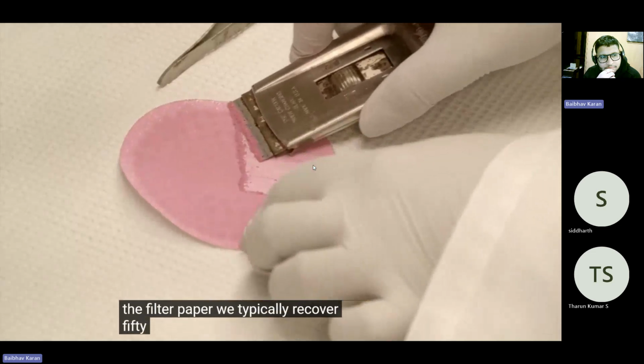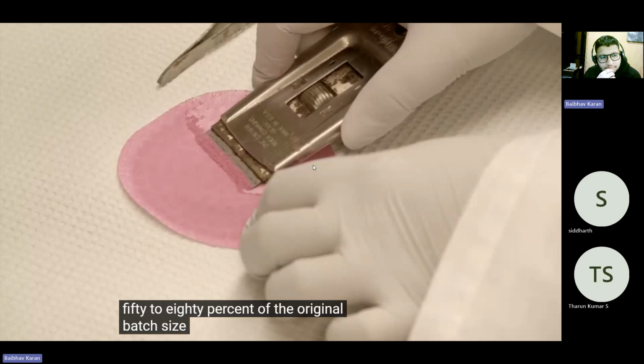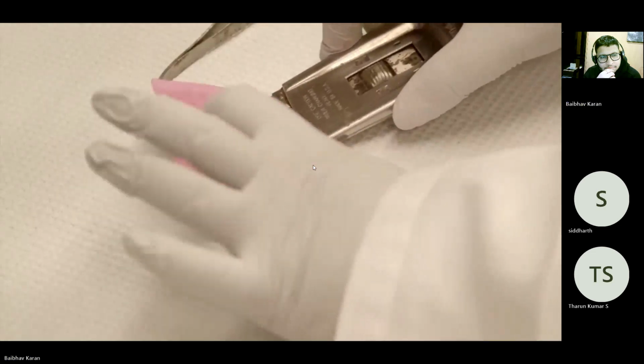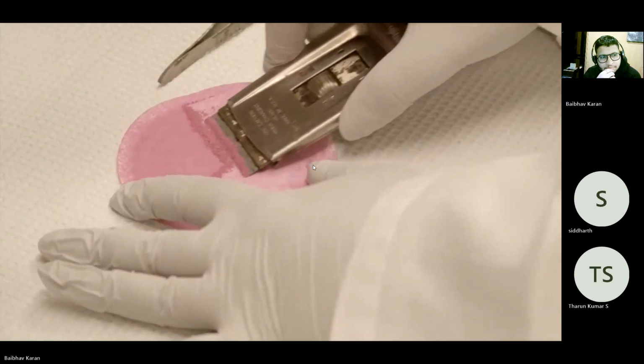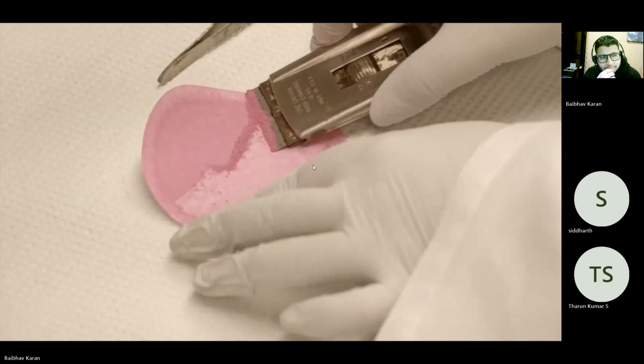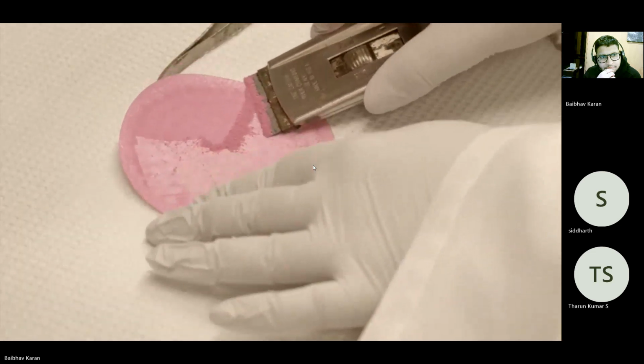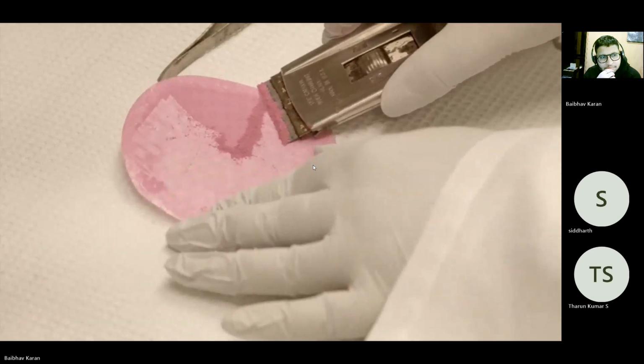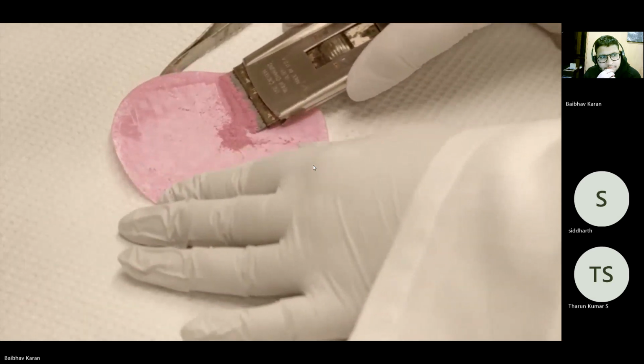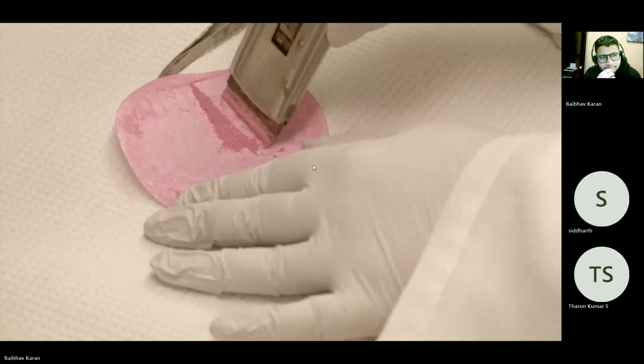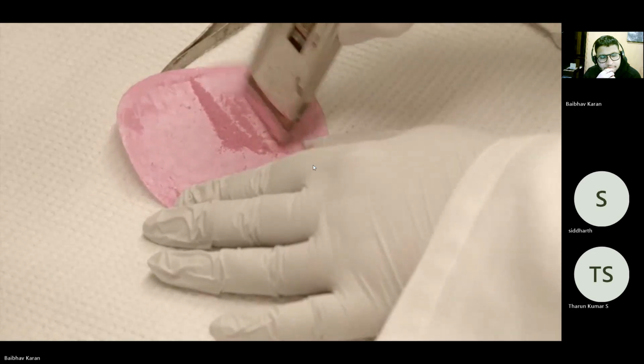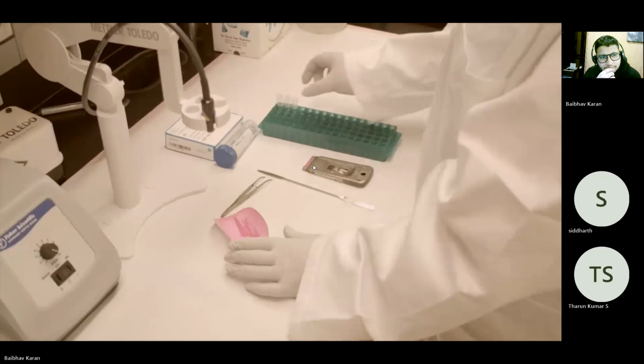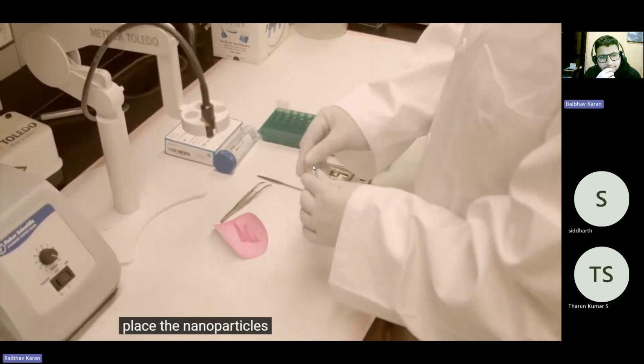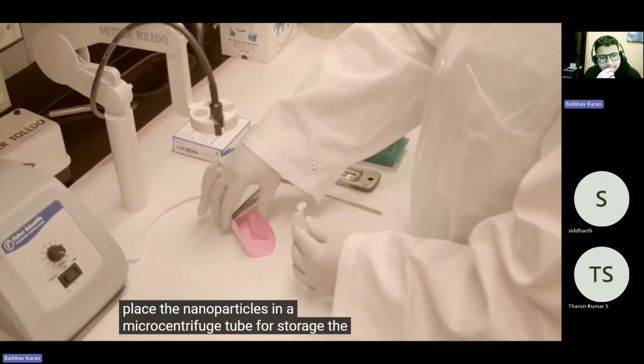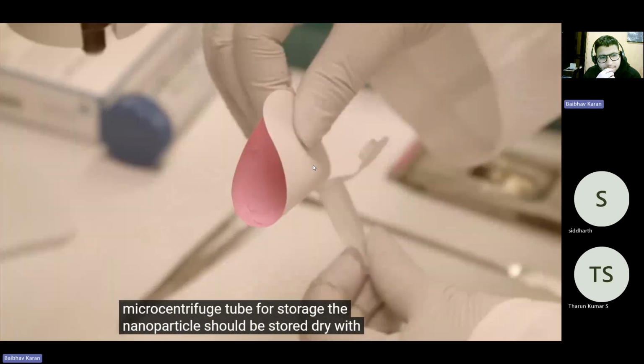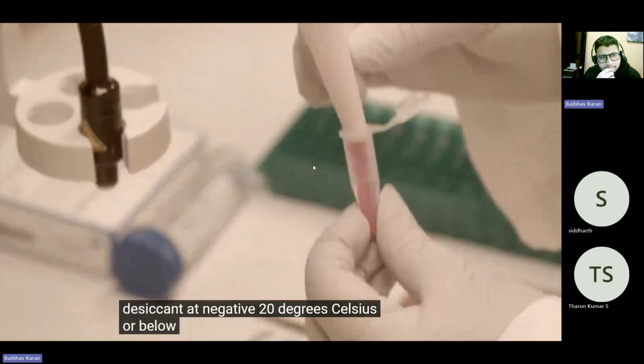We typically recover 50 to 80% of the original batch size. Place the nanoparticles in a microcentrifuge tube for storage. The nanoparticles should be stored dry with desiccant at -20 degrees Celsius or below.